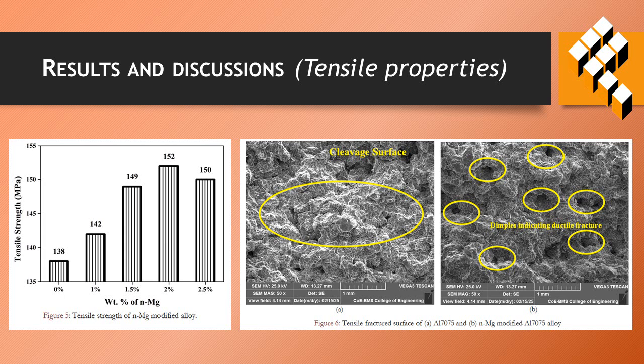From the outcome, it is observed that more cleavages were found in the base material, whereas in the nanomagnesium modified alloy, the fractured surface showed more dimples, and these dimples indicate the fracture was ductile fracture.